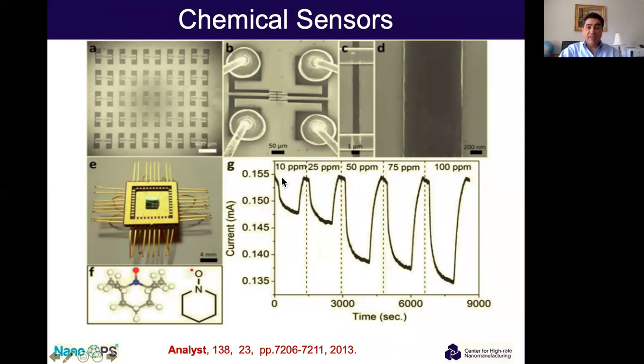So you can see here, when you have 10 ppm of hydrogen sulfide, the current goes down, which means the resistance increases, and then when you expose it to air, it goes up, and you keep repeating this. And basically the same thing happens, and the base resistance stays the same throughout. And we had sensors made a few years ago. We still have sensors made 2-3 years ago, and they still work.